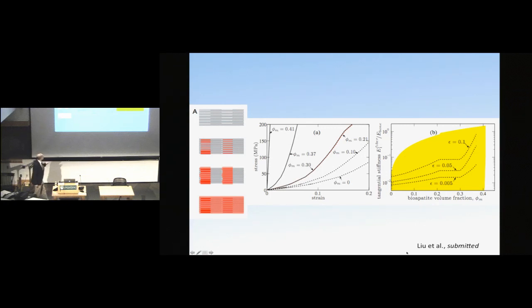And we can see this as well here. This is all nonlinear. You can see that the modulus increases only mildly. So this is a plot of modulus versus the amount of mineral inside one of these fibrils at various levels of strain. This is nonlinear, so the response is different at different strain levels.